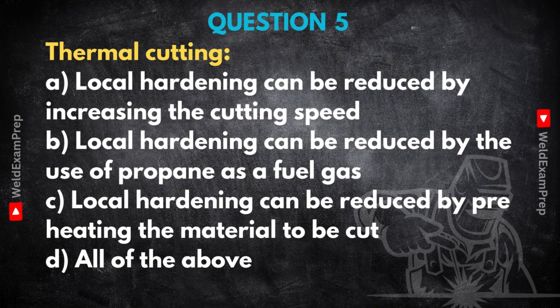Okay, so local hardening, what are we talking about? When you thermally cut certain steels, especially higher carbon or alloy steels, the area right next to the cut gets very hot, then cools down very quickly because the surrounding metal acts like a big heat sink. Rapid cooling. Very rapid cooling. And that can cause the steel in that narrow band, the heat-affected zone, or HAZ, to transform into martensite. Martensite. That sounds familiar. Very hard, right? Extremely hard, yes, but also very brittle. Think glass hard. Not something you generally want on the edge of a component as it's prone to cracking.